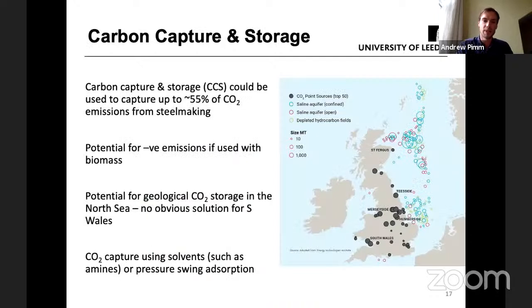Because there are so many sources, it's typically expected that CO2 capture could only be used to capture up to about 60% of the emissions. And if you then account for about a 90% capture rate, which is typical for, say, amine solvents, then you're looking at around 55% of CO2 emissions being captured. However, as I mentioned before, if you were to combine this with biomass, you could potentially get down to very low, or possibly even negative emissions.